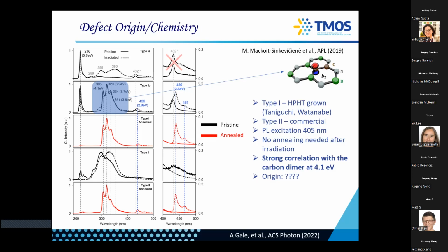And we can take another defective HBN. So this is, again, no UV, no exciton emission and no UV emission, very broad, not the carbon defects, and there is nothing forming. And then we can just repeat with type 1 annealed, create this carbon dimer here, 4.1 eV, and easily create our 436 nanometer emitter. So very deterministic, very reproducible, and we now can control in which HBN material we can actually create these defects. Huge step towards actually engineering something on demand.